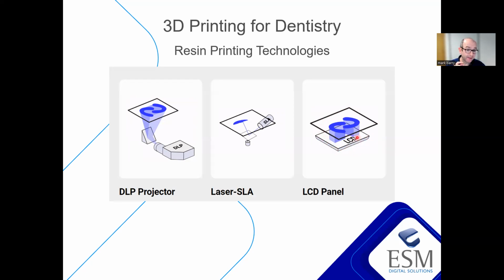But the LCD panel, a liquid crystal display, sorry, like a typical calculator display, that gray surface where areas are turned on in black to create the numbers and the shapes. So what happens with the LCD panel is it selectively becomes opaque, it selectively allows light to pass through. And that light is ultraviolet light generated by the LED panel, and therefore we're creating the pattern for each particular layer. So irrespective of whichever one of these solutions is being applied, an image is being created, and the resin is going to be cured in a layer by layer manner.